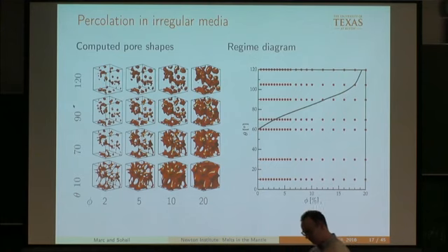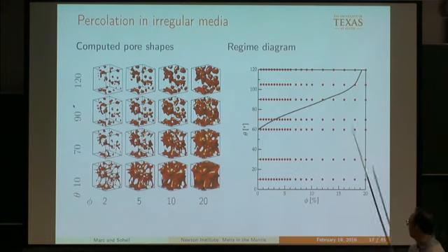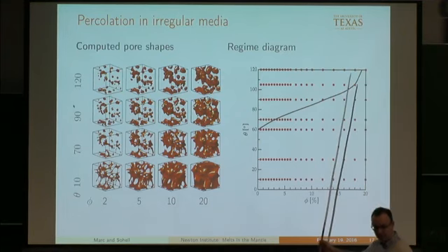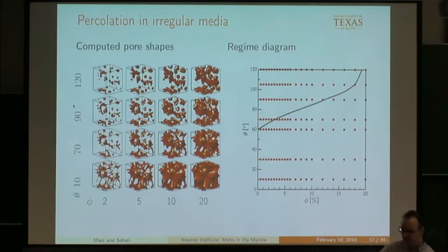The other thing that we've noticed is when two pockets connect, they actually contract a little bit, which makes it then harder to connect over to the next set of pockets. And so together, all of these effects make for a very large, up to essentially almost 20% percolation threshold. And so, of course, percolation threshold is harder to define in this case because you have both isolated and connected pockets.